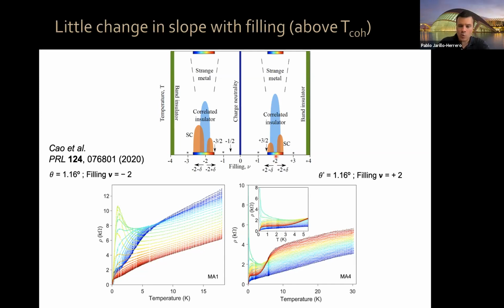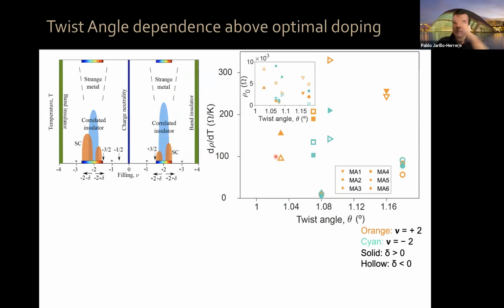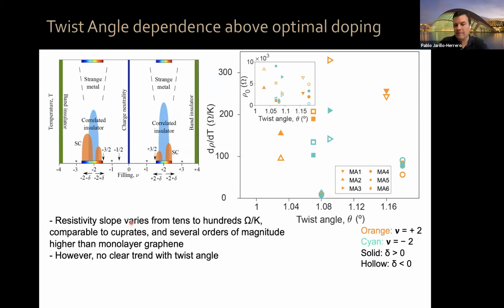Now, we can investigate both the slope, d rho dT, for the system, as well as the offset. It turns out the resistivity slope can vary from tens to hundreds of ohms per Kelvin. The middle of this range is comparable to the cuprates. On the high end, like 300 ohms per Kelvin in some cases, it's actually quite a bit larger than the cuprates' resistivity slope when you normalize by thickness. And it's several orders of magnitude higher than in monolayer graphene.